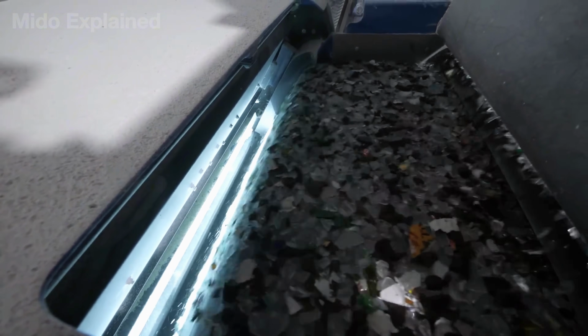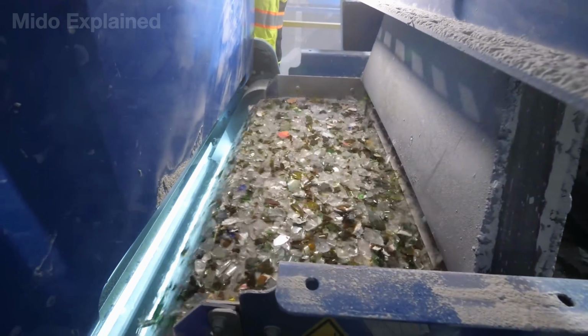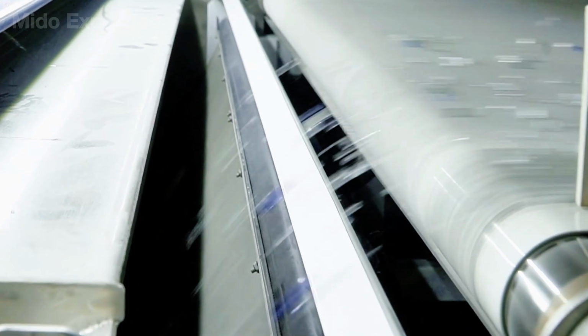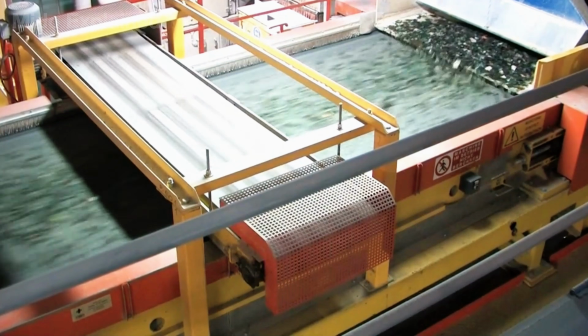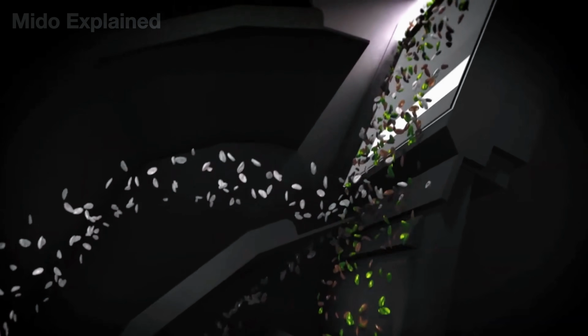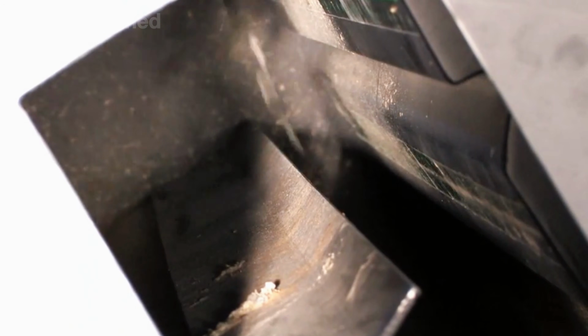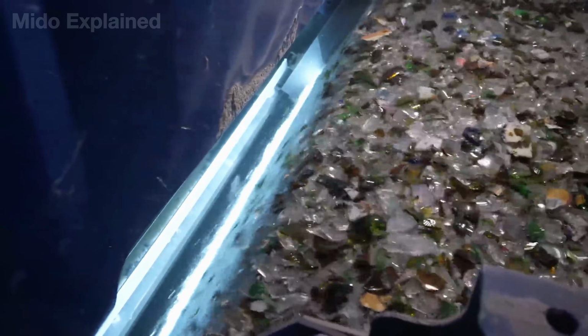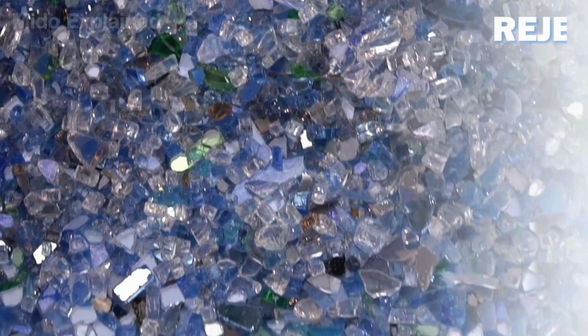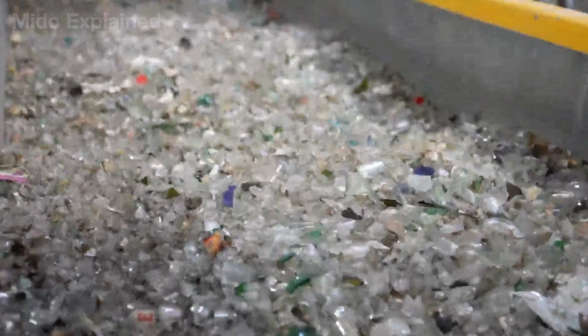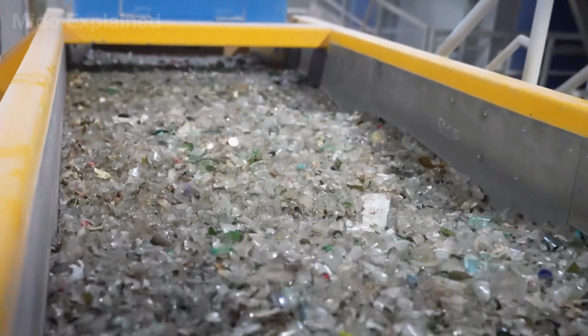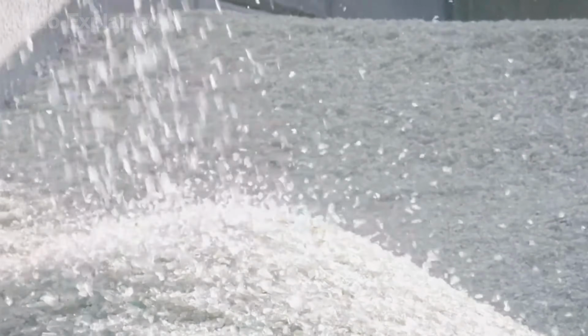High-resolution cameras and optical sensors positioned above the belt continuously scan the glass fragments at a rate of tens of thousands per minute. Upon detecting a color difference, the system triggers compressed air jets to blast each fragment onto its corresponding conveyor belt. Clear, green, and brown glass are completely separated, as even a tiny amount of colored glass contamination can alter the color of an entire batch of molten glass. Consequently, this stage typically achieves an accuracy rate of over 99%, ensuring a uniform supply of raw material before the glass enters the furnace.